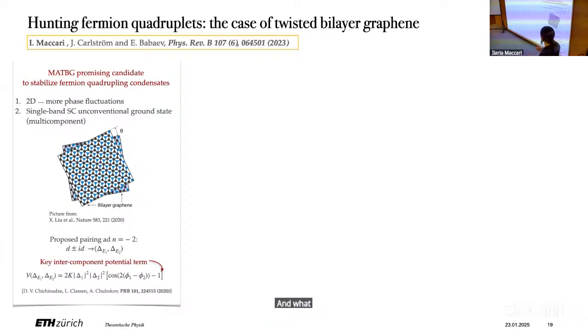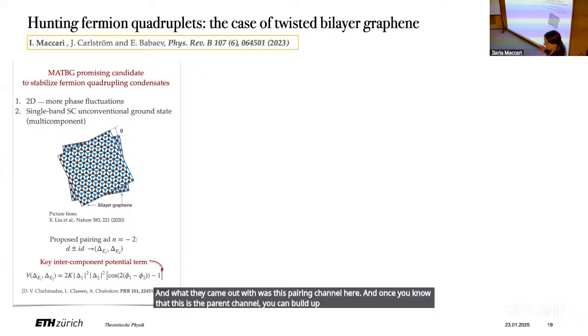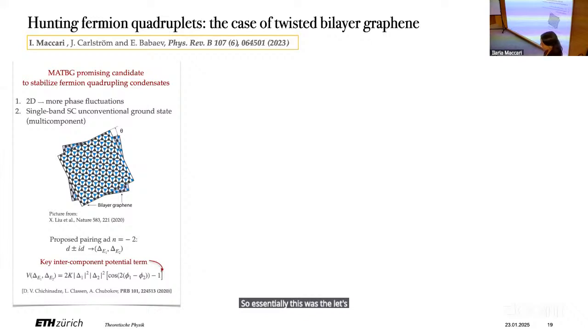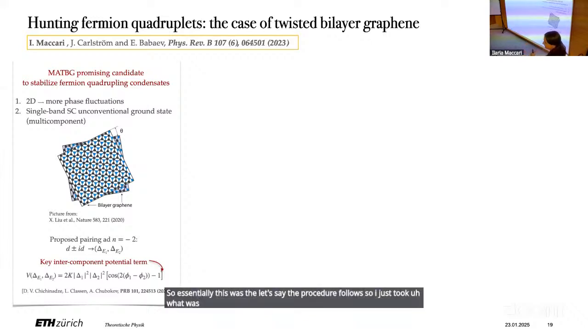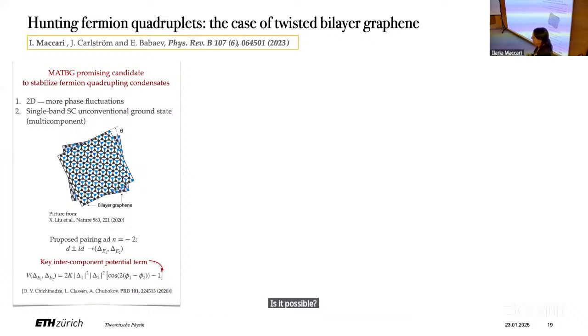And what they came out with was this pairing channel here. Once you know that this is the pairing channel, you can build up a Landau functional that respects the two-component nature of the superconducting pairing and the crystal symmetry of the system, which in this case is hexagonal. So essentially this was the procedure followed. I just took what was derived as the Ginzburg-Landau functional coming from a microscopic model. But then, in your calculation, can you see, for example, the length scale of the vortices compared to the moiré length scale? From my calculation, I take it for granted, so I cannot see the moiré structure.